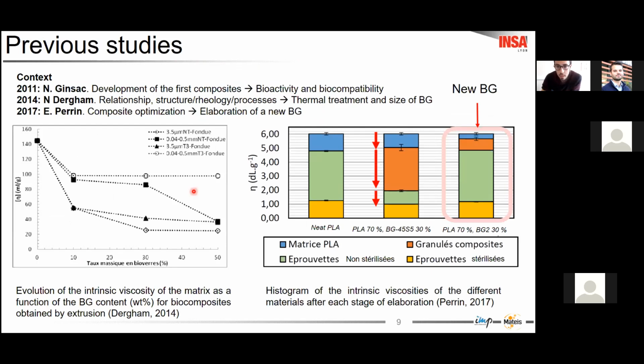In the Matéis and EMP laboratory, 3 people work on this type of biocomposite. In the following two graphs, I show you the results obtained by Nora Dergham and Eloise Perrin during her thesis. In the graph on the left, you can observe the evolution of intrinsic viscosity as a function of filler content. We can see that viscosity decreases with filler ratio, except for the biocomposite with bigger particles and thermal treatment.